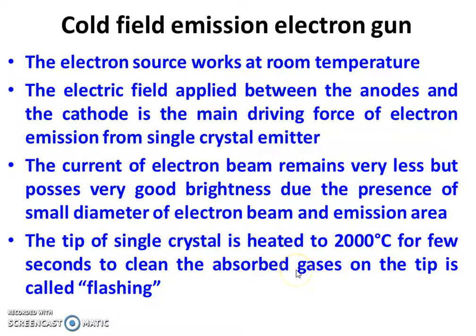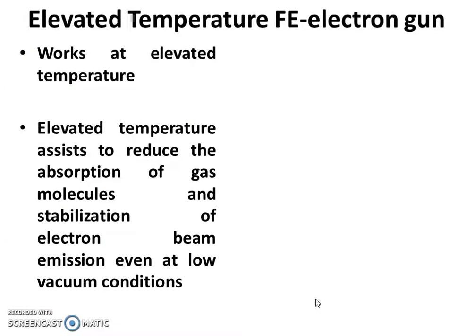The tip of the single crystal is heated to 2000 degrees centigrade for a few seconds to clean the adsorbed gases on the tip, and this process is called flashing. After that, the temperature is reduced to room temperature. The elevated temperature FE electron guns basically work at elevated temperature, which is why the name is elevated temperature field emission electron guns. Elevated temperature assists in reducing the adsorption of gas molecules and stabilizes electron beam emission even at low vacuum conditions.